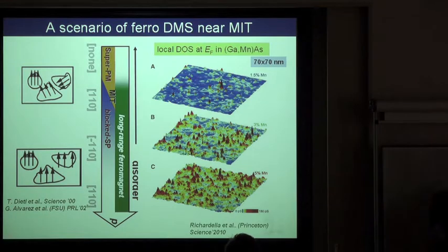And this has an enormous effect on magnetic properties, because if we have locally more carriers, we will have locally more magnetic order. So looking at this kind of picture, we can suspect that we have local superparamagnetic grains, which we can order if we go to low temperature, or we can order them if we go to high magnetic field. So this kind of result immediately demonstrates that we should take very seriously into account the presence of what we call phase separation, nanoscale phase separation into regions which are more polarized and regions which are less polarized. And these regions may be disordered at higher temperature and more ordered at lower temperature or field.